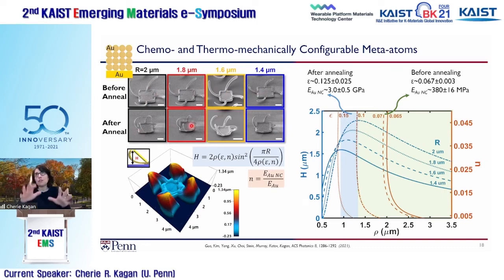So all of these were done with the ligand exchange, and then they're released. What we take advantage of here is that when we release the arms, we're using an etching process to get underneath, but it won't get underneath this middle pad. It's too big. And so we can release the arms, but still keep them bound to the surface if we want. And so we could do all sorts of measurements mechanically to show that we could really build up.